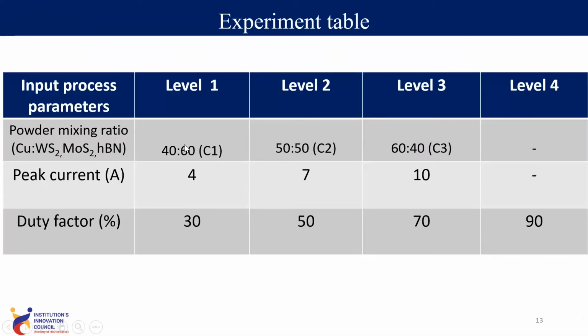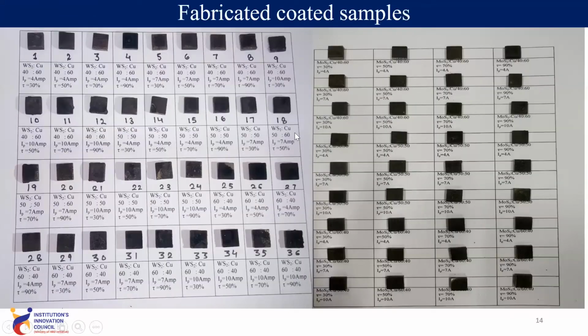In the experimental table, these are the powder mixing ratio that is varied, peak current 4 ampere to 10 ampere, duty factor 30%, 50%, 70%, and 90%. These are the fabricated coated sample images. As you can see, these are 36 experiments that are performed using copper WS2 tool and copper MoS2 tool. 36 experiments that we have performed, and I have shown these surfaces after the coating.